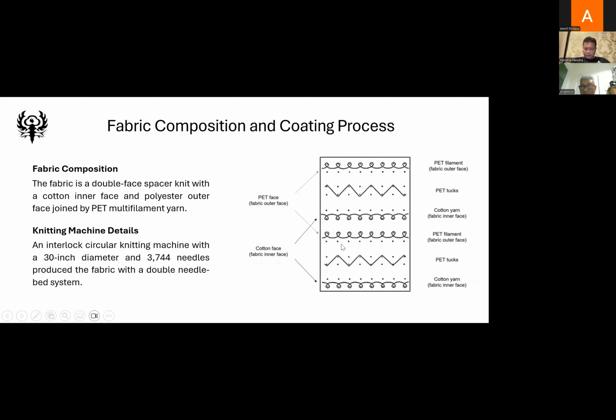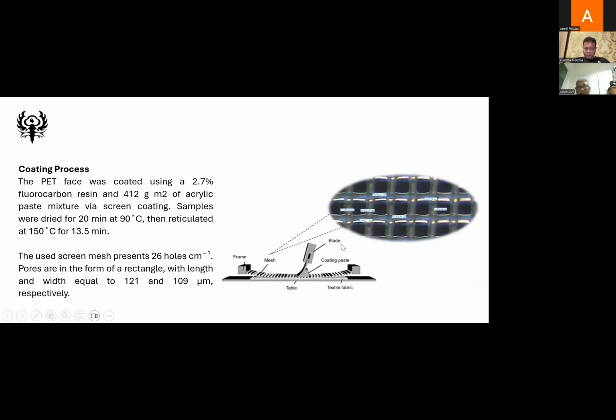The construction of the fabric. And then this fabric goes to the coating process on the polyester face, with 2.7% fluorocarbon resin in 412 grams per square meter of acrylic paste, using screen coating. The samples were then dried for 20 minutes at 90 degrees Celsius, and reticulated at 150 degrees Celsius for about 14 minutes.